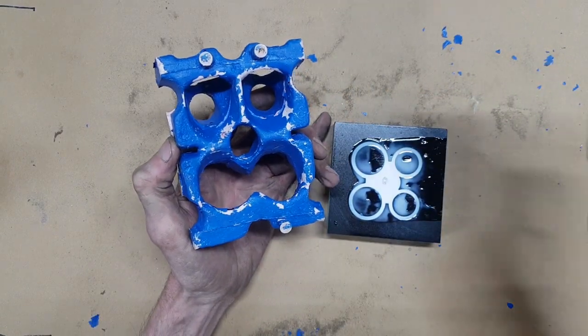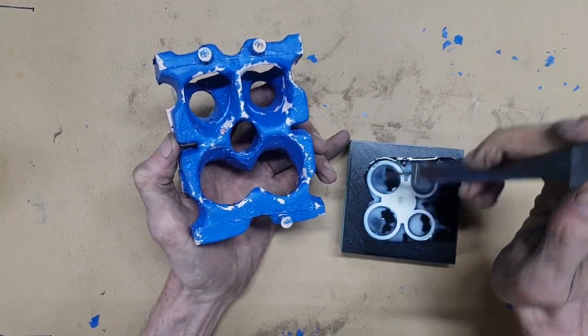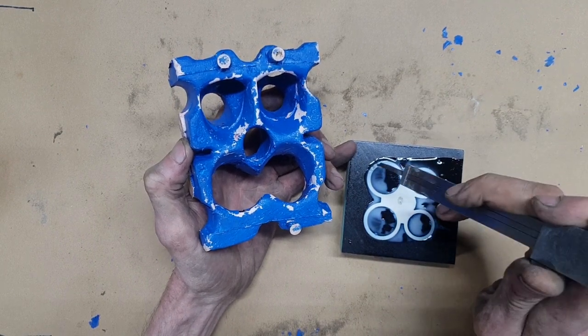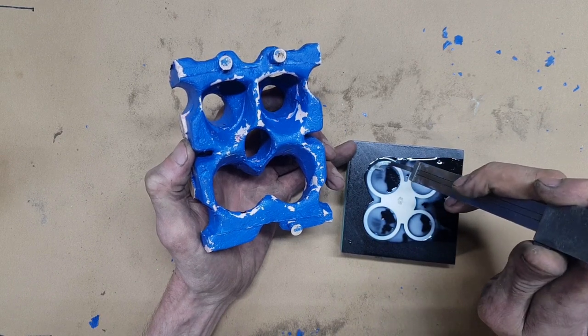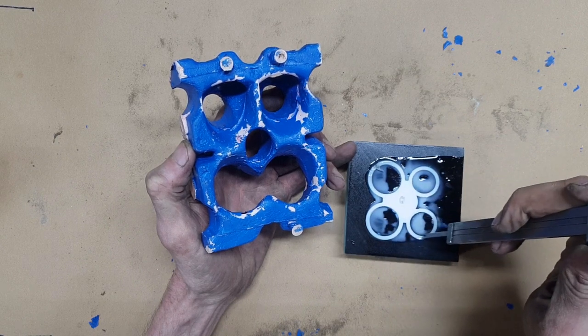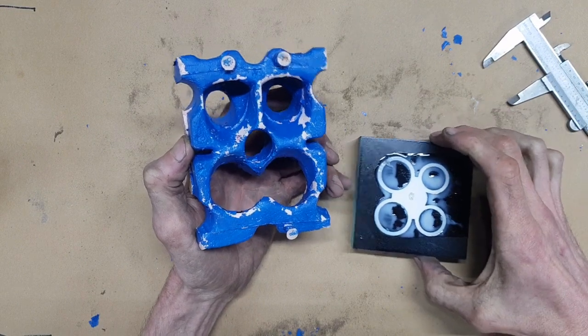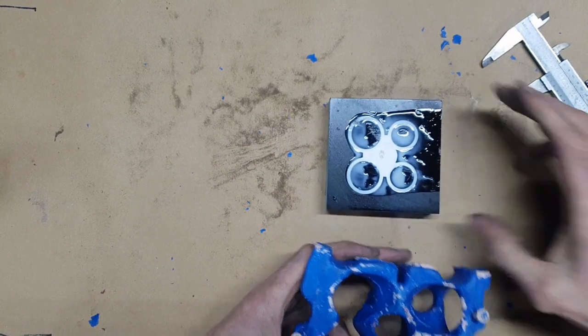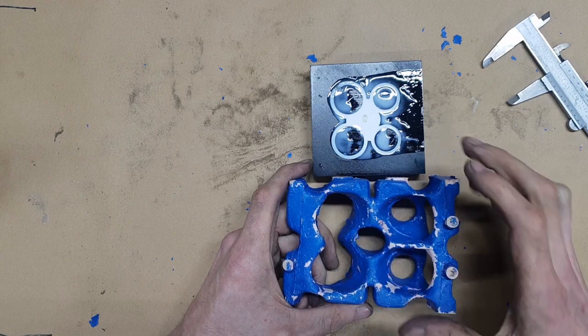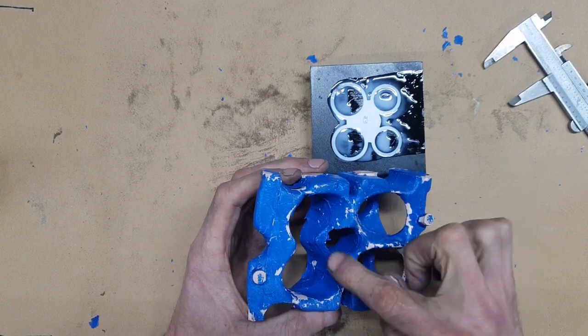You can see these are still soft here, which means if this was aluminium, they would have solidified first. This would be last. So this is still molten. These are still solidifying. So this is all in risk of a hot tear area here, and with the exhaust ports. Now, just so that you know, it's that way. I know you know, but there's a big mass here. So I would say they scrapped a lot of these heads because of that reason. There's just a huge amount of aluminium here.